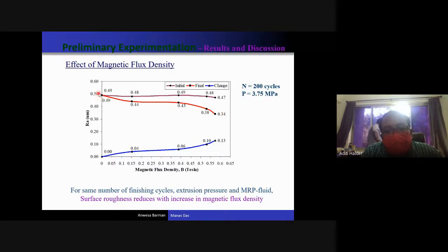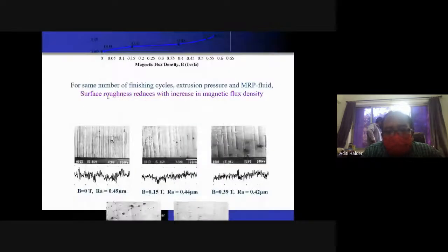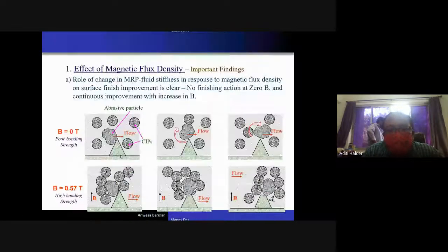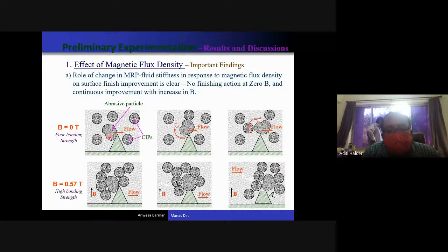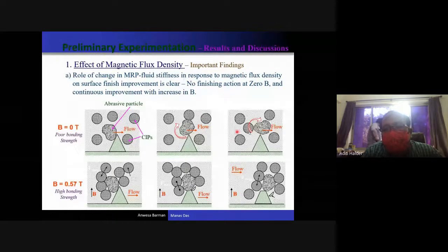at different magnetic fields. We can see here that at zero magnetic field there is no finishing, because in this MR fluid the CIP particles cannot take part in the metal removal. When you apply zero magnetic field, the abrasive particles are not bonded by the iron particles. So whenever these abrasive particles come in front of roughness peaks, they rotate over the roughness peaks without cutting.